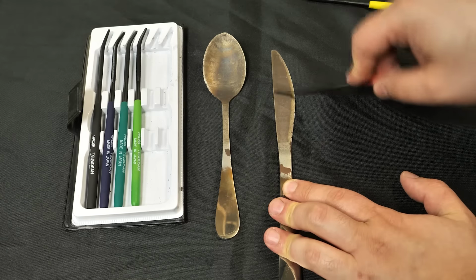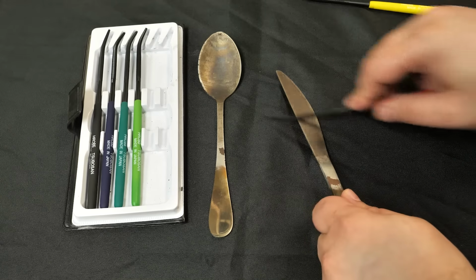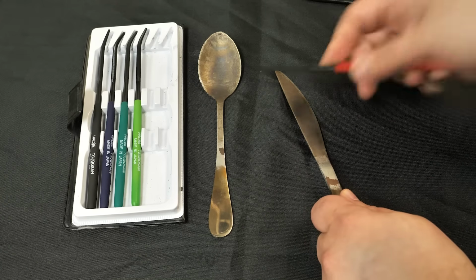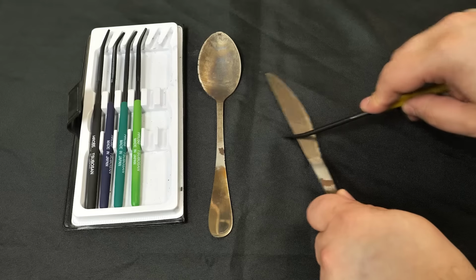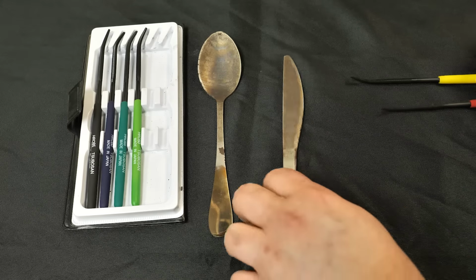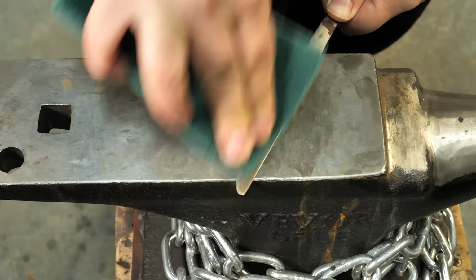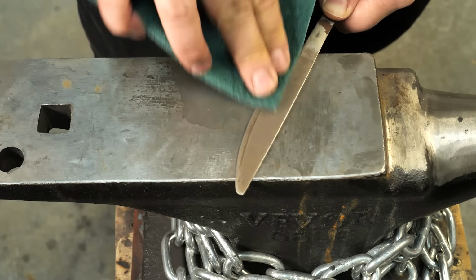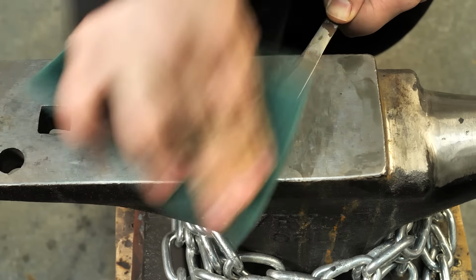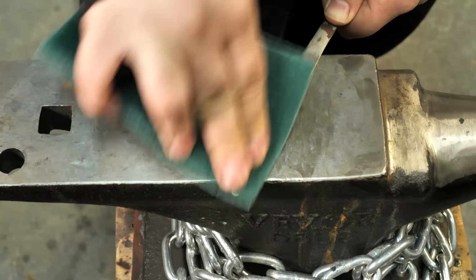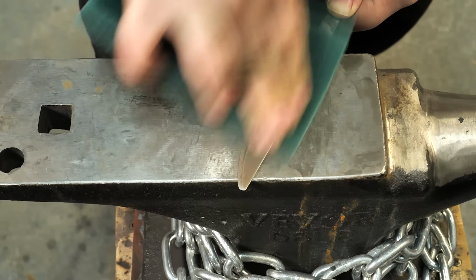The cool thing about this is that it even works on cheap stainless steel, so I can take an otherwise blunt butter knife, sharpen it, and then dunk it in the salt bath to make it into a hard cutting implement. Though the surface comes out looking pretty rough, so a very light polish is probably in order. The nitrogen-rich layer is not very deep though, so you don't want to polish it right off.